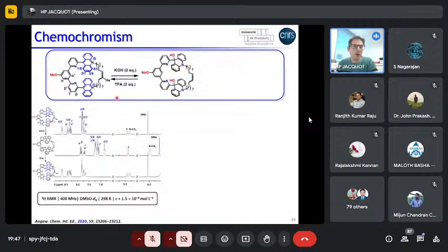Then also, Johnny looked at the chemochromic properties of the macrocycle. So he converted the bis-acridinium derivative into the corresponding bis-acridane upon addition of hydroxide ions. You can follow the dearomatization of the acridinium cores by proton NMR spectroscopy, and this system can be fully aromatized under acidic conditions and more especially using TFA. Then this new macrocycle has no affinity for perylene.